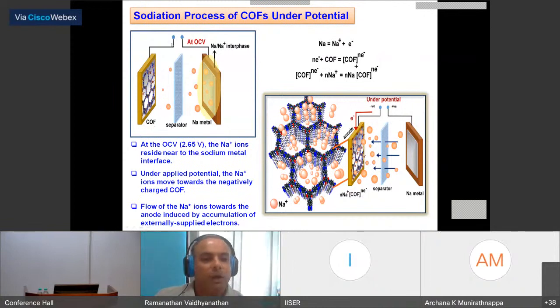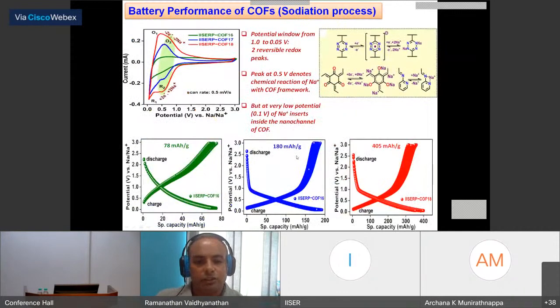anode, because now this anode is going to suck all the electrons from the outer circuit and become highly negatively charged, which sets up an excellent driving force for the sodium ions to come and sit. And also the flexible nature of the COF will afford no volume expansion, so it will be very capable of staying the same, and a lot of sodium ions can be loaded, which directly relates to the anodic performance. And this is what is shown here.